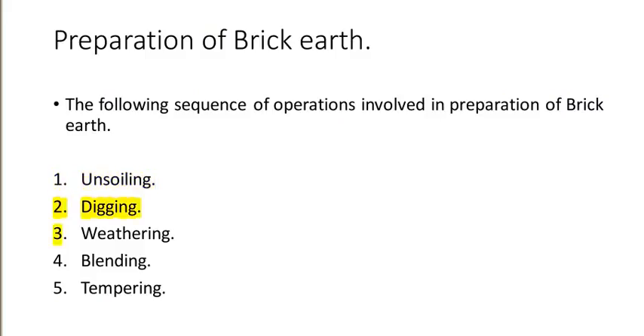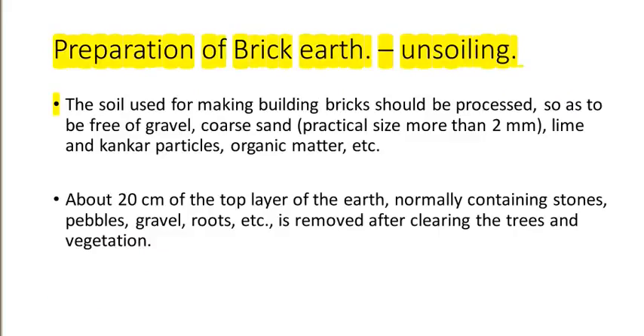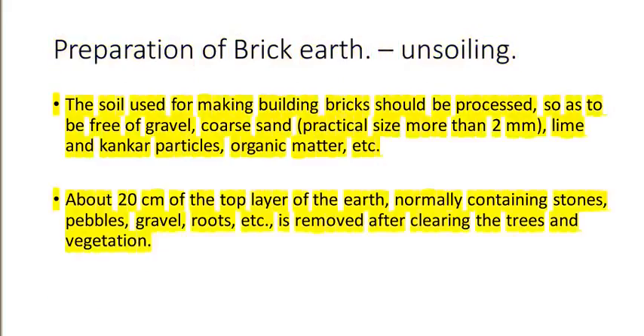Preparation of brick earth — Unsoiling. The soil used for making building bricks should be processed so as to be free of gravel, particles more than 2 mm, lime and kankar particles, organic matter, etc. About 20 cm of the top layer of the earth, normally containing stones, pebbles, gravel, roots, etc., is removed after clearing the trees and vegetation.